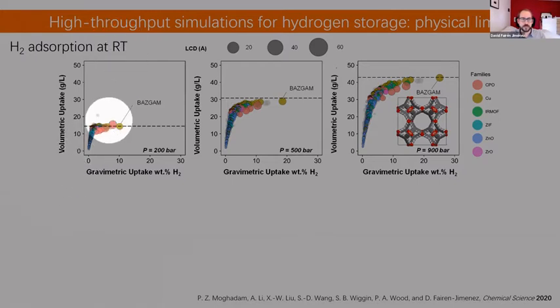In this case, not with hypothetical materials that were in the previous slide, but with real materials that have been synthesized, we can really see the evolution at different pressure. All these different colors that you can see here are related to the MOF families that we were defining. So we can really find the most optimal material.